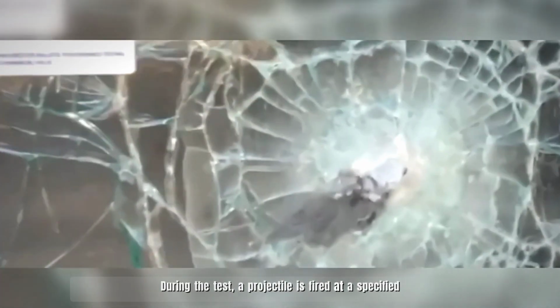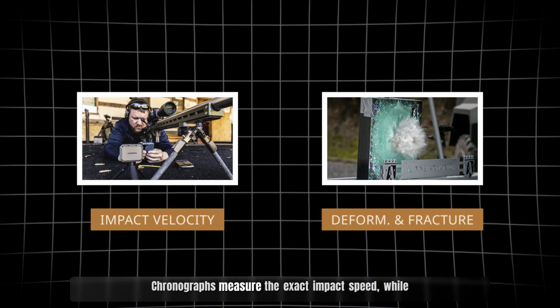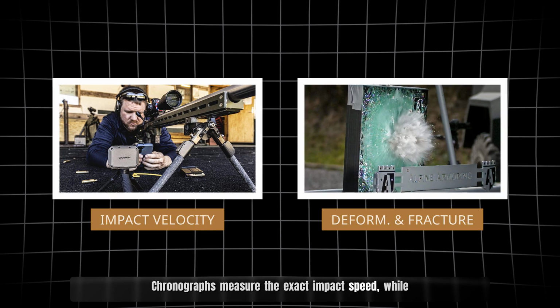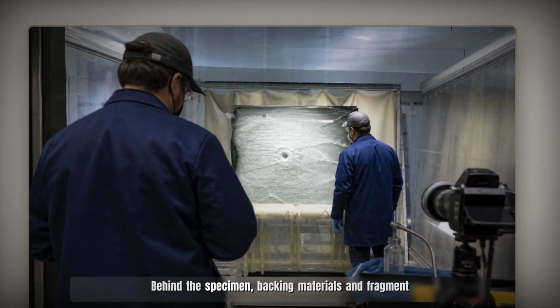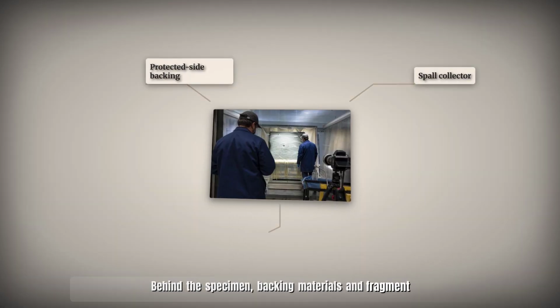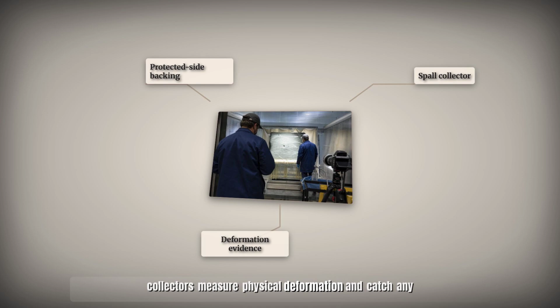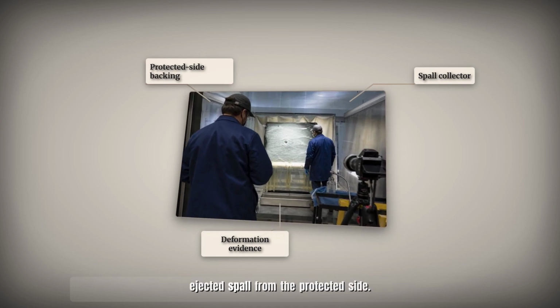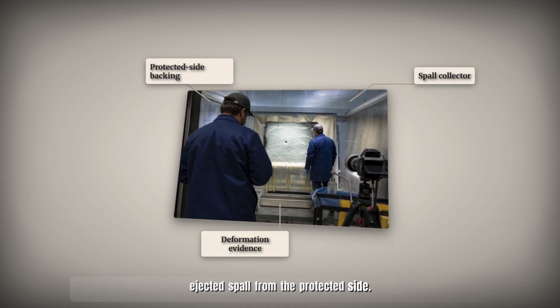During the test, a projectile is fired at a specified velocity, angle, and shot pattern. Chronographs measure the exact impact speed, while high-speed cameras capture deformation and fracture propagation. Behind the specimen, backing materials and fragment collectors measure physical deformation and catch any ejected spall from the protected side.